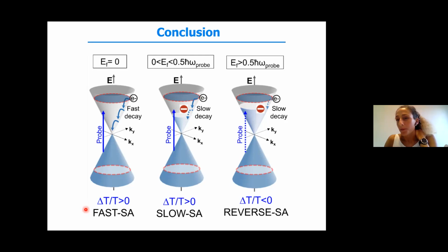What I can say is, for example, if you want to have a backgate in silicon, which does not allow for measurement in the near infrared in transmission, in that case the response in reflection can of course be measured. We must consider that where we have graphene deposited on a silicon substrate, the response will again be dominated by the variation of the transmission, which is double passing through the graphene and is reflected by the silicon substrate.